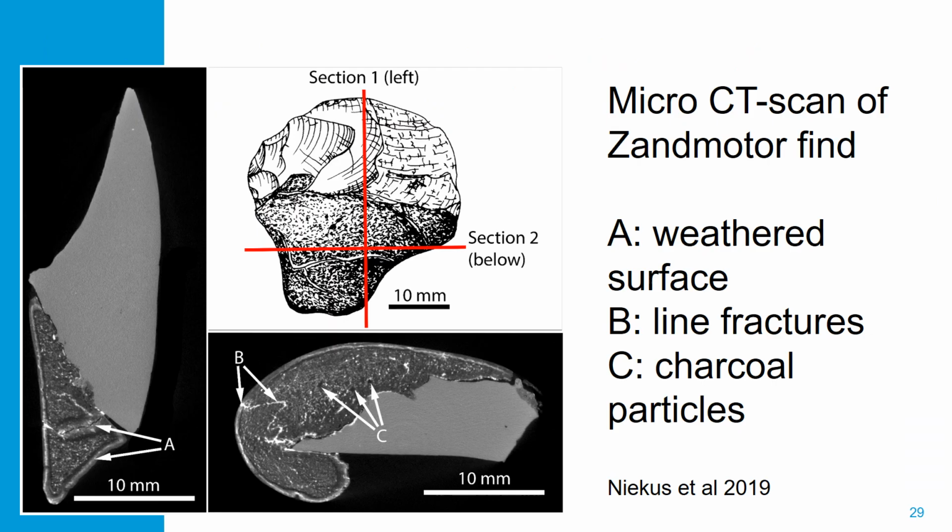So, which method did Neanderthals then use in the end? To do that, we studied the contamination pattern of the particles in the tar with a CT scanner. And this showed that very fine sand and pieces of charcoal were spread throughout the tar very homogeneously.